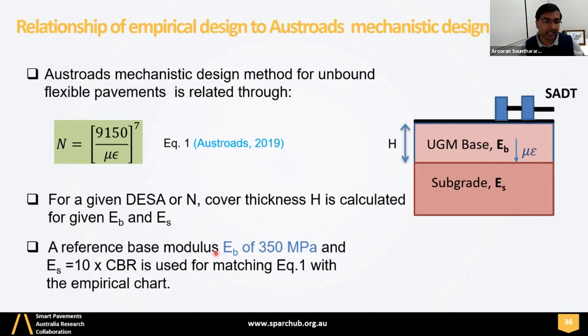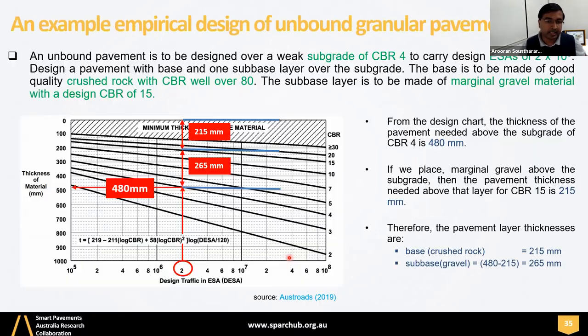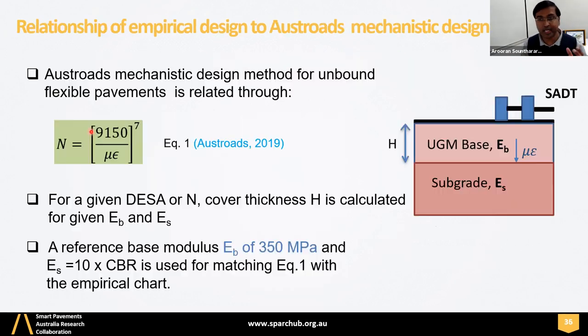So I want to make one reference here. The reference base modulus EB is 350 megapascal, right? So this empirical chart is developed based on the unbound granular material modulus of 350 megapascal. The one thing missing in this empirical design is that the unbound granular material modulus is not captured. So how it is captured in the Australian mechanistic approach is through this finite element software analysis. So they change the modulus here, and then the vertical strain is changed according to the modulus you select for UGM, right? And then that strain is essentially used in this equation to calculate the allowable number of repetitions for the performance of the subgrade, which is rutting.